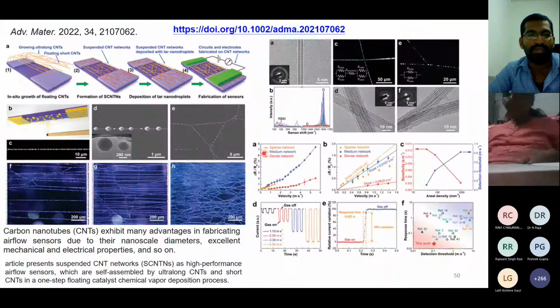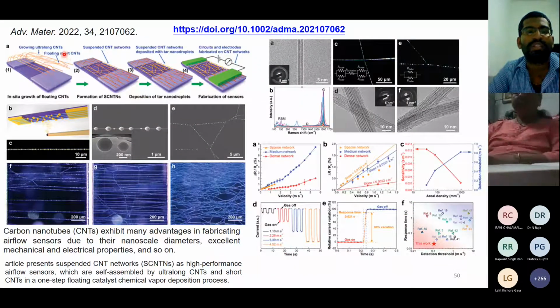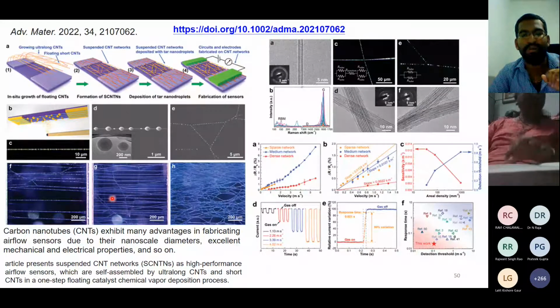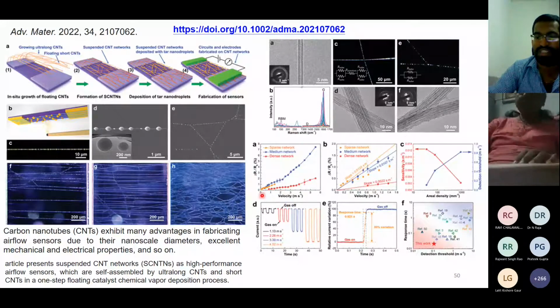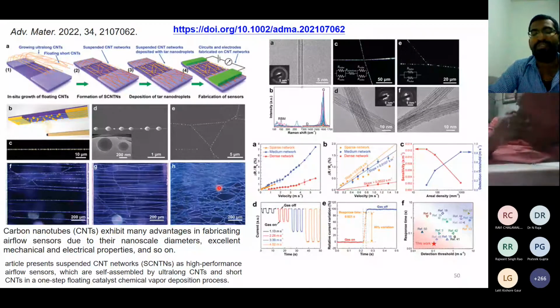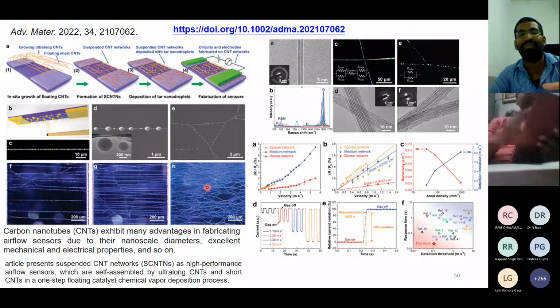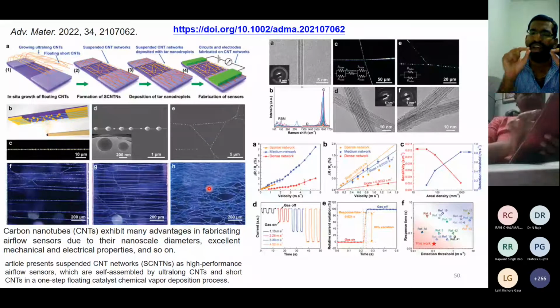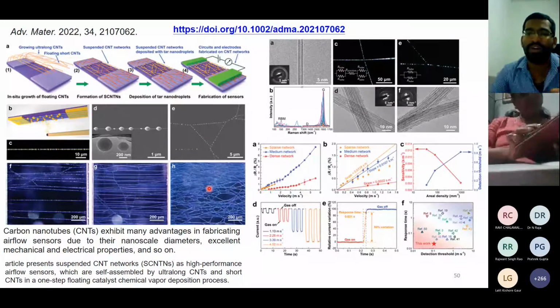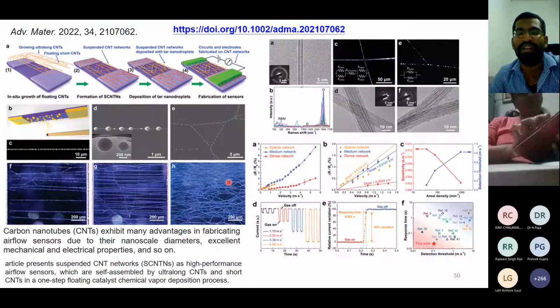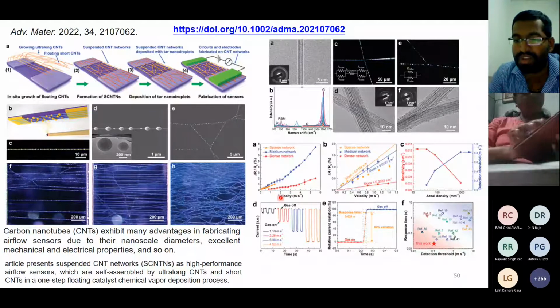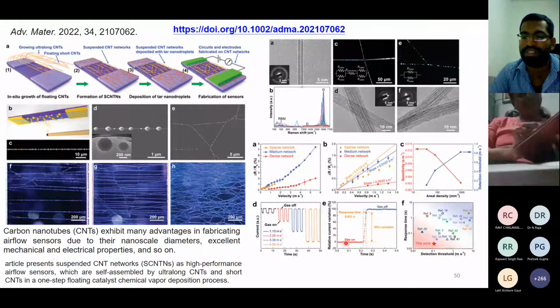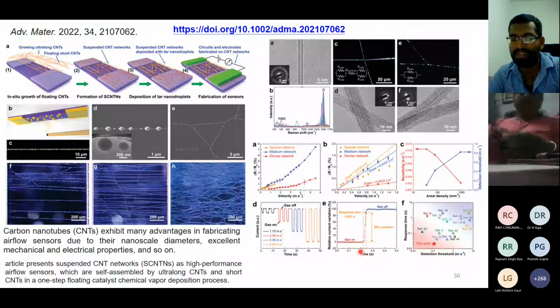And the other one is they are using some CNT, carbon nanotubes. This kind of conductive filler they use to make three different layers. One is very sparse, very thin, and the other one is a medium structure and the dense structure. They also optimize the conditions like this, and then they monitor their sensitivity. Before, I explained with the help of silica nanowires; in this case they change to a different conductive material called carbon nanotubes. This is also a 1D structure and it's very, very small. So here we can see the difference among different densities. For example, this one is very sparse, this is medium, and then this is dense. If you have a medium structure, you are able to end up with a very good sensitivity. So they are demonstrating this, and here you can see the response upon gas flow. This kind of variation can be monitored, and this is going to help you to monitor your wind speed, all these kinds of things you can do.